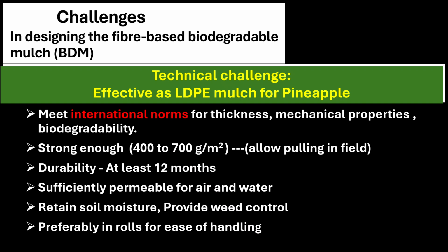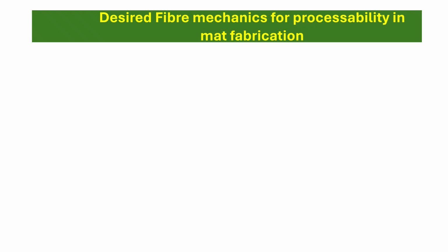So it should be of certain thickness that it can be easily manipulated, and also it can withstand the outside conditions for at least 12 months, because we should not forget that pineapple is a long cycle crop, so the mat should be of a long duration in the field. And also it has to play some similar role as the plastic film, so like retain some moisture to a certain extent, prevent weed from growing, and be permeable to air and water, of course. So to ensure that the final product is sufficiently strong and durable, we have to use appropriate processing technique, and also use the appropriate fibers.